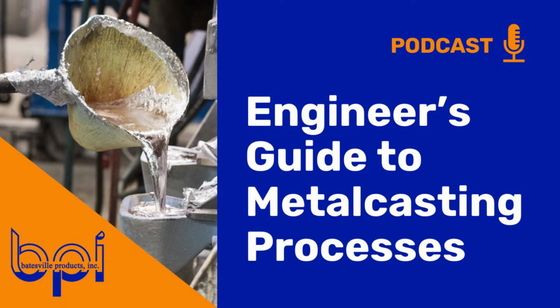Hey guys, we got a quick question about the as-cast inserts. How much easier is that with permanent molds, and is it more problematic with other methods? Sand casting, you're inserting that steel insert or whatever you're inserting into the sand mold, and it's made of sand. There's ways to strengthen the sand to make it more rigid, so you can put that insert in there, and it's possible. It's a little bit more prone to little pieces of sand falling off and contaminating the metal, but it is possible. Die casters really don't want to mess with it.